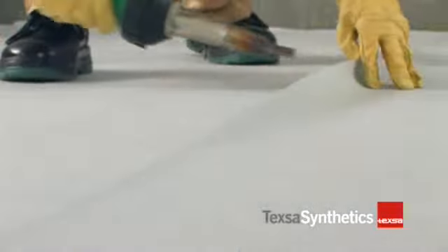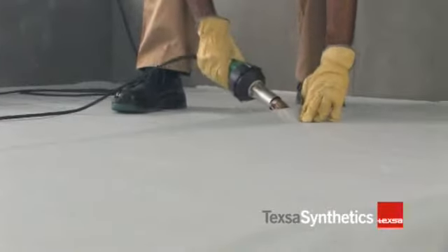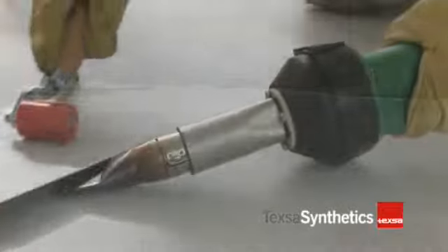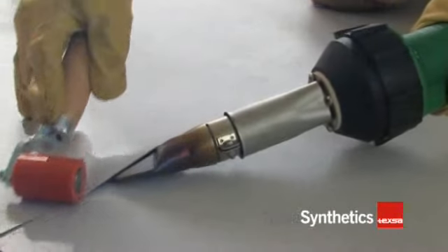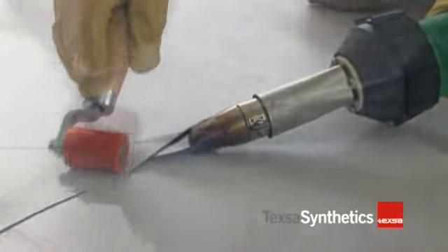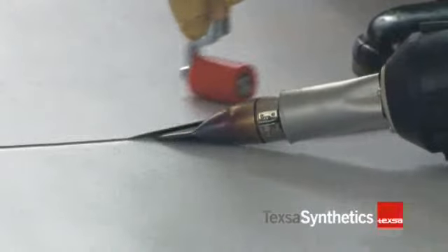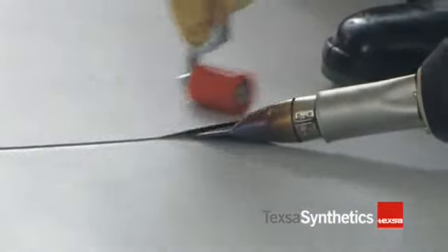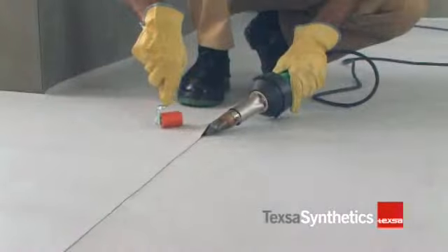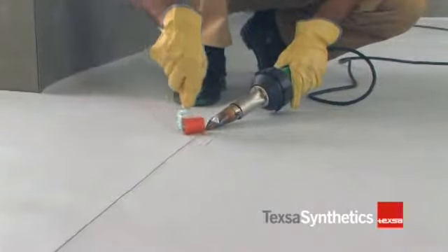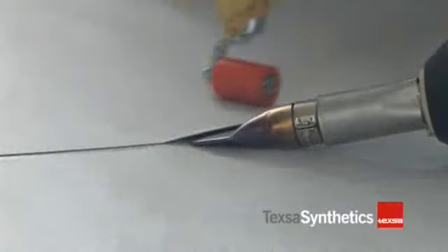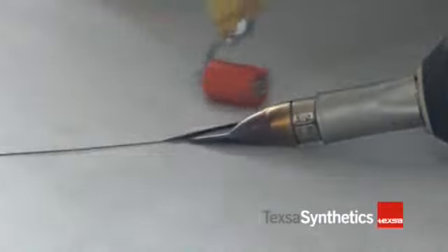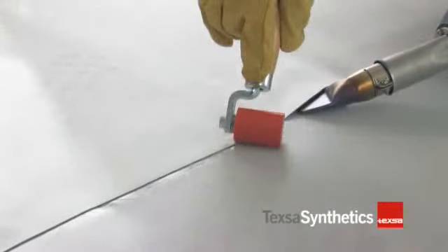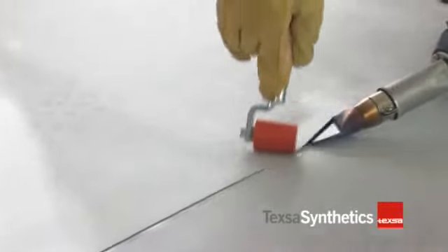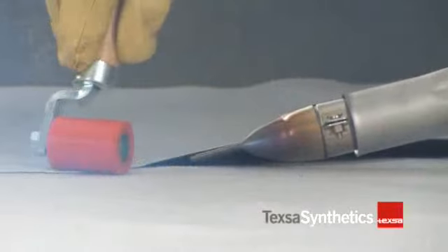It is recommended that the membrane be secured with spot welds every 50 centimeters. Insert the nozzle between the two plies at a 45-degree angle. Move the heat welder along continuously. At the same time, press down with the roller, always moving forward to prevent wrinkles from forming. The weld is correct when a bright strip and a light whitish smoke appear along the seam joint.